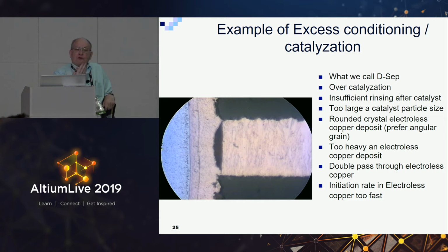Because we're now moving into the era of what we call SAP, semi-additive plating and processing. And that's PC boards that have no copper foil on them. So we're going to make a PC board, and we're going to make a 20 micron trace and space. Well, you can't make really anything under about 50 microns on laminate, because laminate has a weave of glass, and it's not flat enough. So when we start getting below 50 microns, like the iPhone, you no longer use laminate. So all of you that have Samsungs and iPhones, there's no FR4 in your phones.